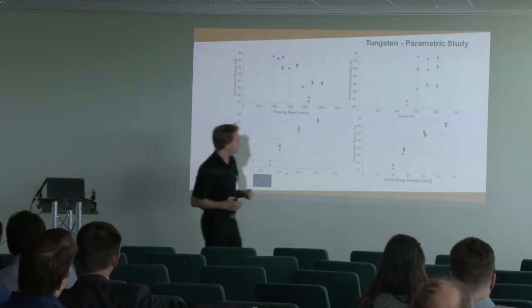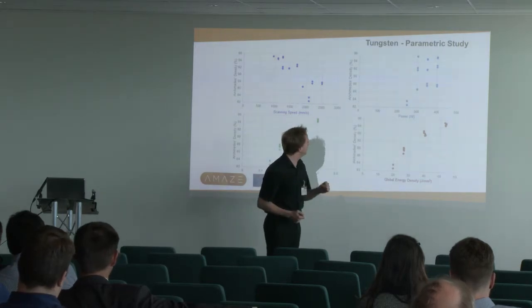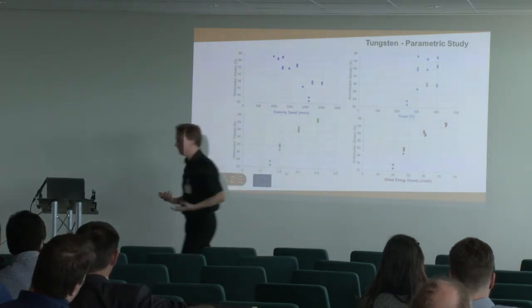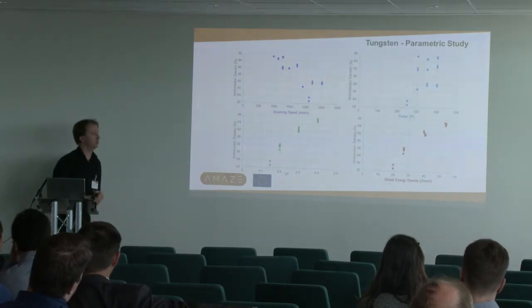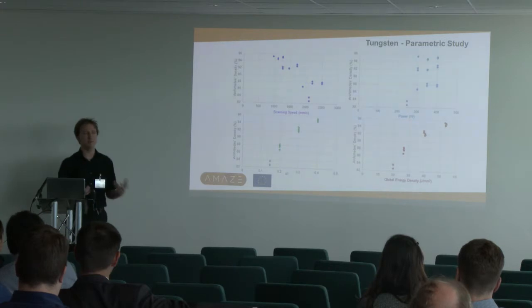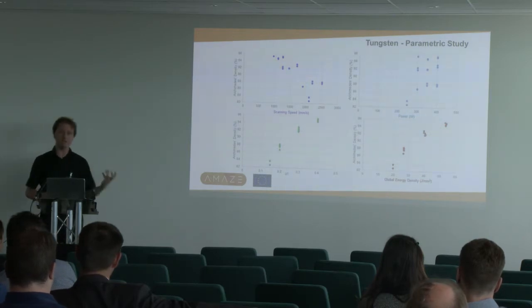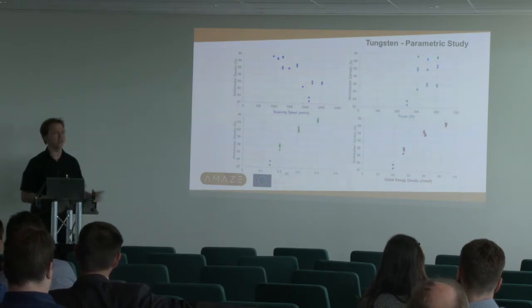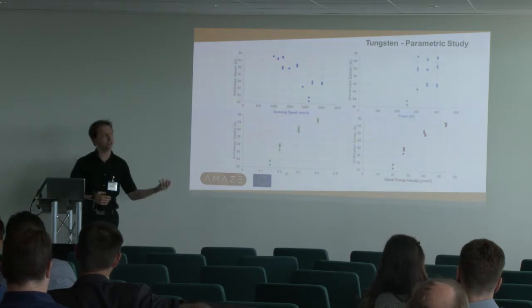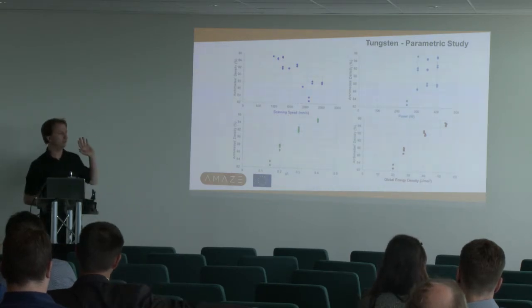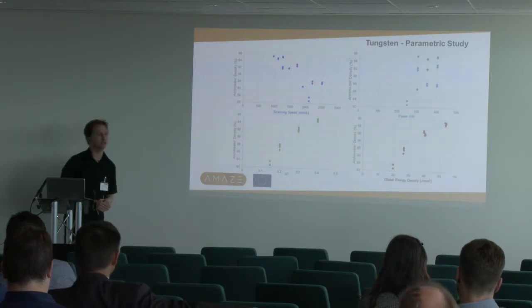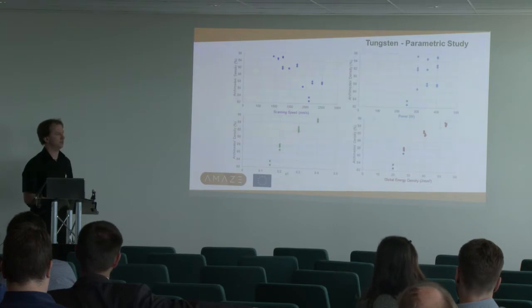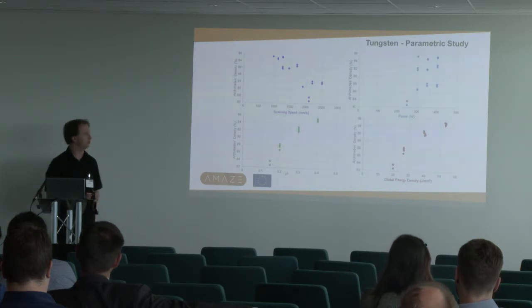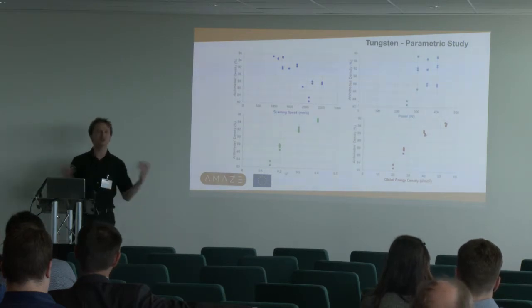And then this bottom right one here, just to confuse everything, is density plotted against global energy density. This is one of the ideas that we're starting to pick up now: maybe there are other combined parameters which are a bit more appropriate. Global energy density is a combination of the power, the speed, but this time the beam diameter. So it's more similar to a linear energy density, and this seems to show a really strong relationship. I'm not saying that this is a complete study yet, and there's still a lot of work to be done to verify that we're doing this correctly, but it is a cautionary tale about using volumetric energy density too widely and too confidently, without appreciating that some of the detail is lost as soon as you start combining parameters.